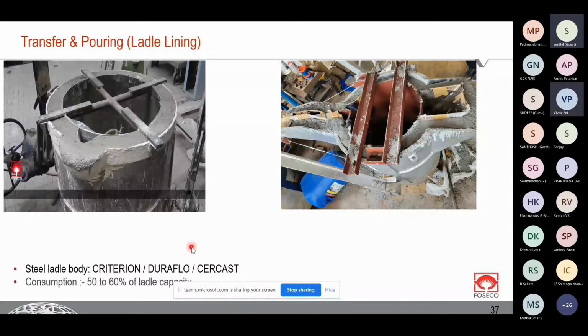Now for the third area, which is transfer ladles or pouring ladles, for both iron as well as steel foundries, we can use a different range of products like Criterion, Duraflow, Cercast. Like in the beginning, we have discussed, based on the cement content, there are different types of refractory. So, for example, Cercast is conventional castable refractory where the cementing agent calcium oxide is more. Then this Criterion is low cement castable. Duraflow is again ultra low cement castable, a self-flowing material, and no cement castable I have not mentioned here, but that product is also there. About consumption, 50 to 60% of the ladle capacity will be the requirement.